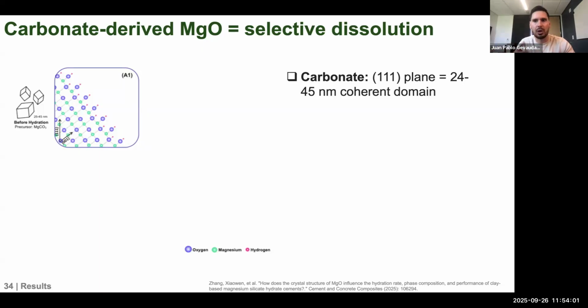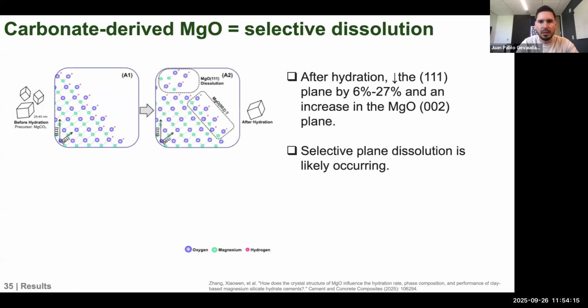And the way that we were able to look at that is by really focusing on the 111 plane of the magnesium oxide produced, which was around 24 to 45 nanometers in that coherent domain through the XRD data that we collected. Now, after hydration, we were able to look at that 111 plane again and see that it actually decreased in terms of that coherent domain, and that what increased in magnesium oxide is the 002 plane, which is aligned with what other research shows in previous work.